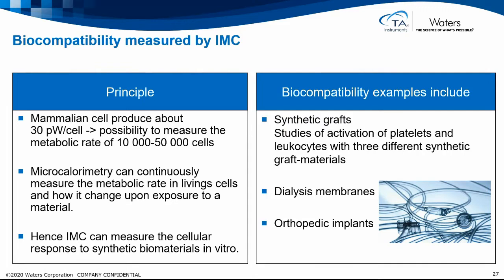Biocompatibility can be measured by IMC by the principle that mammalian cells do produce heat as well. Everything that lives will produce heat. And the metabolic heat of a cell is about 30 picowatt per cell, which means in microcalorimetry we have the possibility to measure the metabolic rate of between 10,000 to 50,000 cells. Microcalorimetry can then continuously measure this rate and see how it changes upon exposure to a material. So we can use microcalorimetry to measure the cellular response to synthetic biomaterials in vitro.